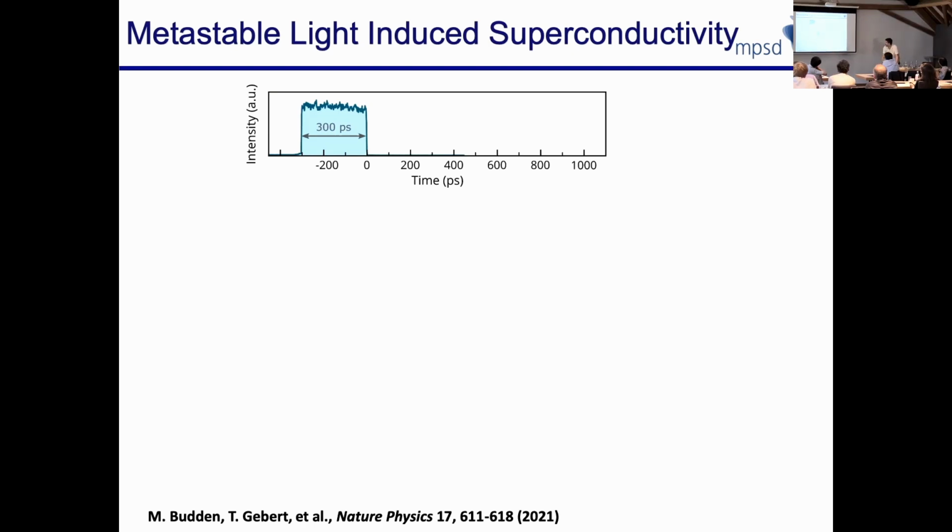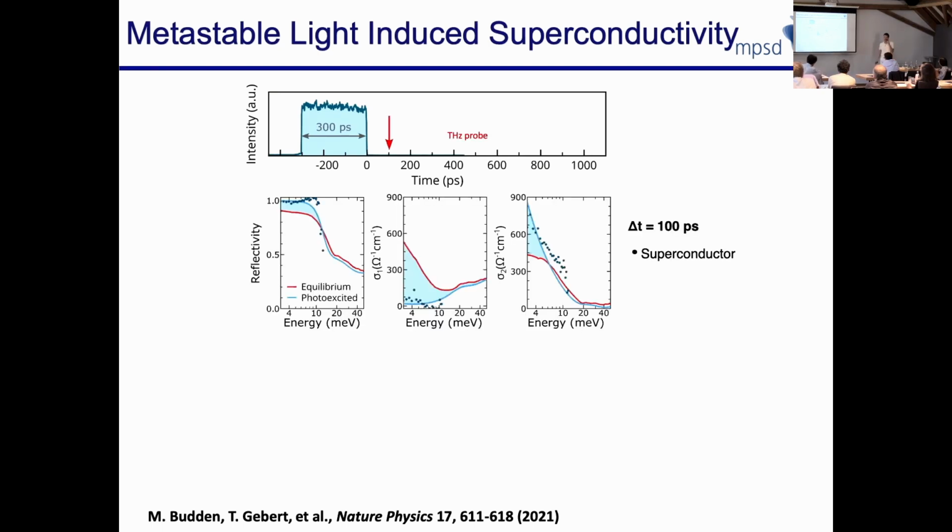And now I'm probing here 100 picoseconds after the pump pulse is gone. The experiment is done at 10 hertz and not at 1 kilohertz, so the signal to noise is what it is, but it's still convincing, we've done this many times. You see that 100 picoseconds after the pulse is gone, you still have this divergence, something that can be fitted with a divergence that goes in the same place where the previous one went. You have a gap and a reflection coefficient of order 1. This is larger than 1. Don't ask, I will talk about this at the end.